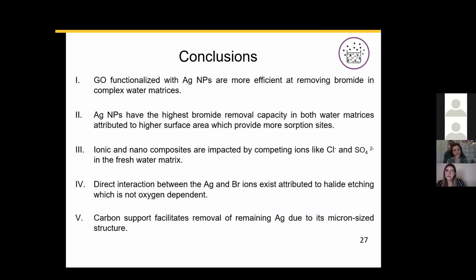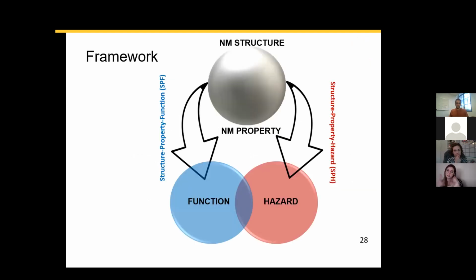However, we also see that competing ions, namely chloride, sulfates, and phosphates, will definitely have an impact on how these materials remove the bromide from the water. But some of the mechanisms that we see are direct interactions between the bromide and the silver nanoparticle surface, creating this etching ability. We also saw that the carbon actually facilitates the removal of silver.